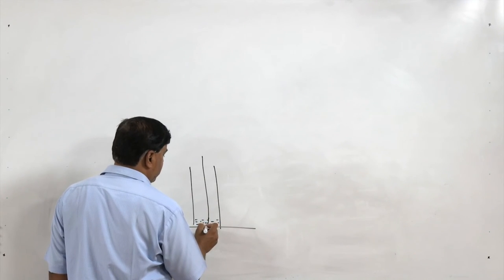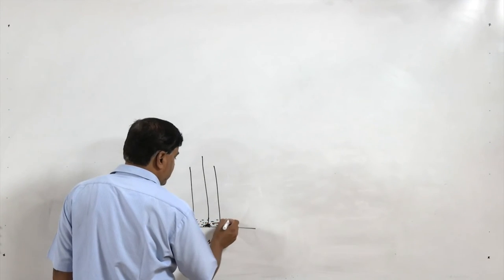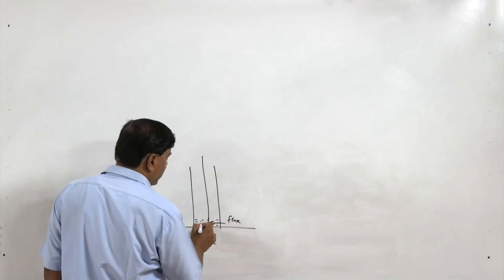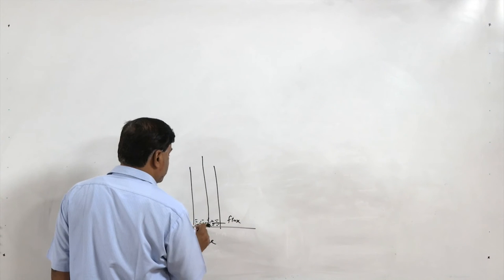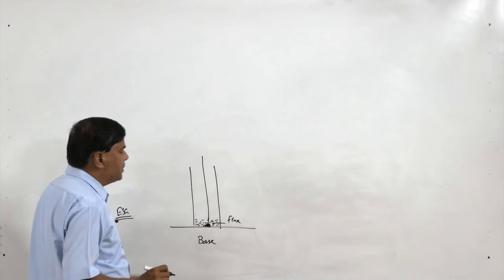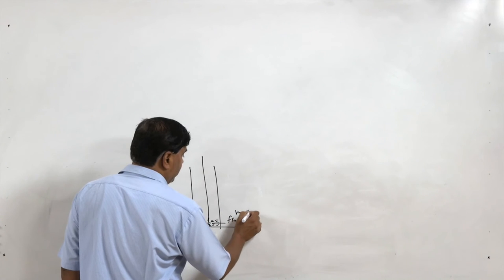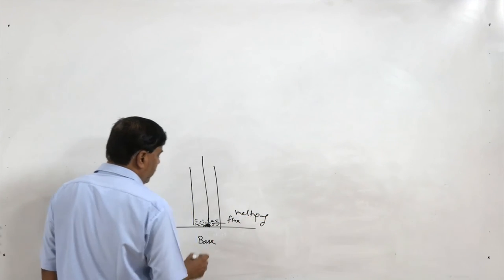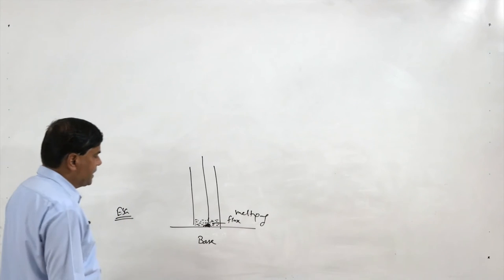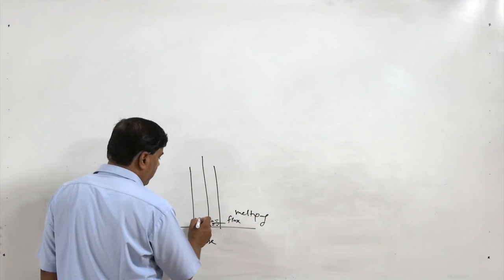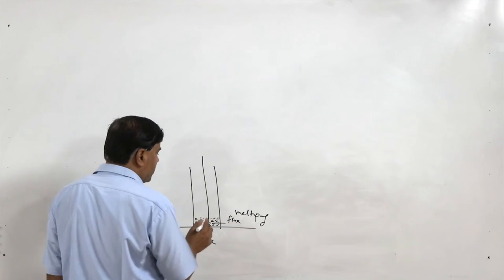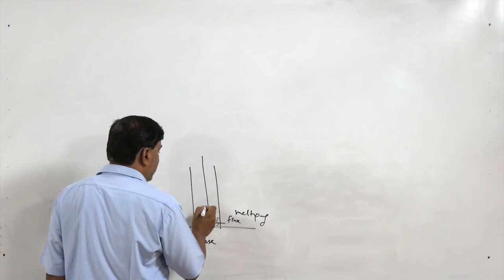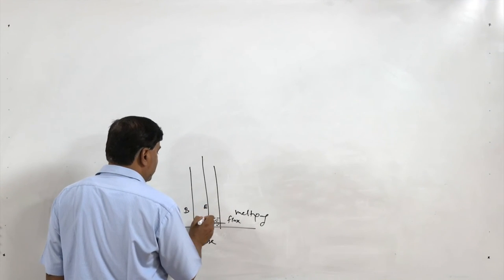it touches the base plate, sparks are there. So this arc helps to initially melt the flux. So melting of the flux is achieved through the heat of the arc. So heat of the arc is primarily, in the beginning, used for the melting of flux. Once flux is brought to the molten state and a sufficient pool of the bath is created, the arc gets extinguished and the flow of current from the electrode to the base starts through